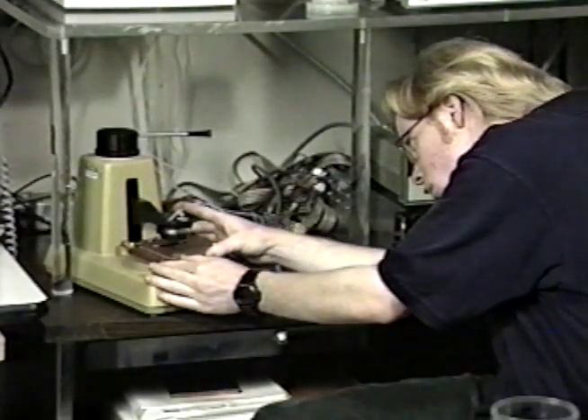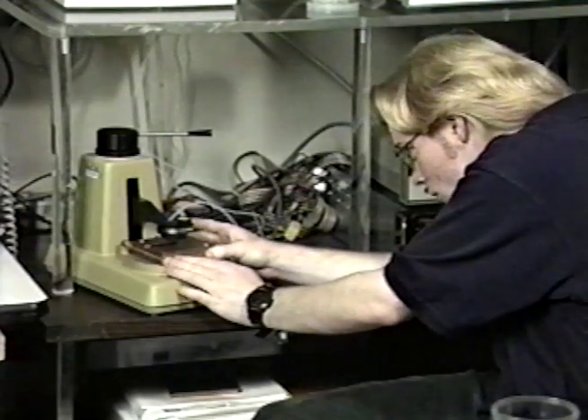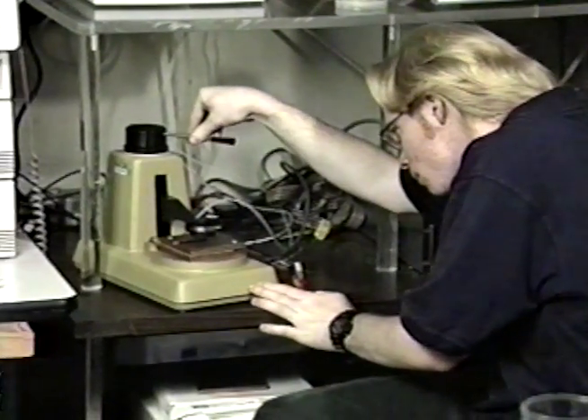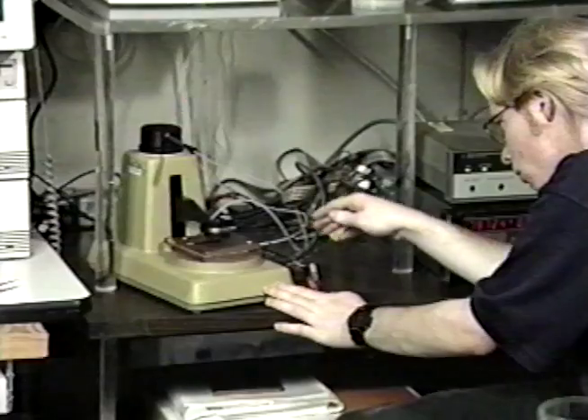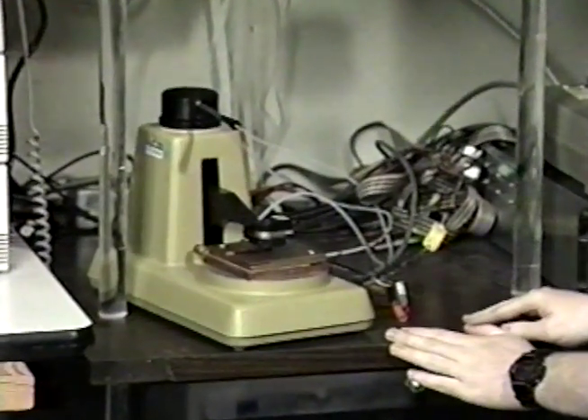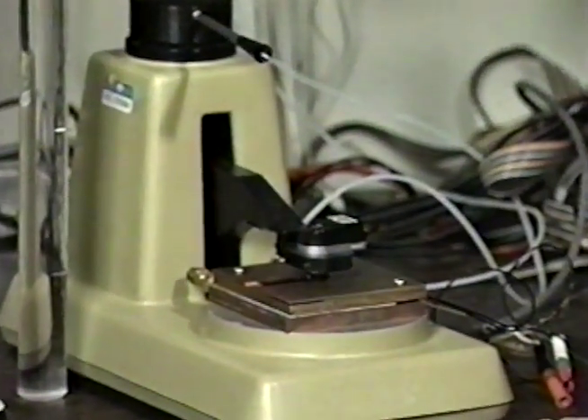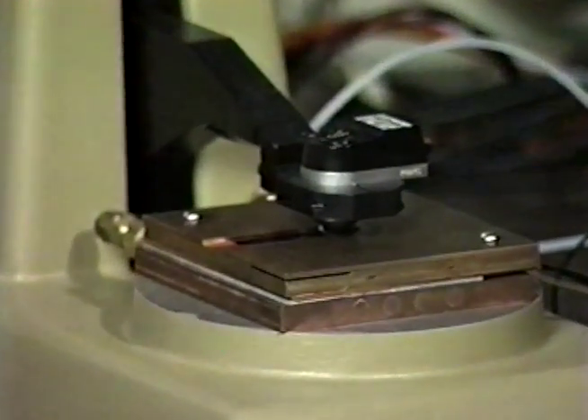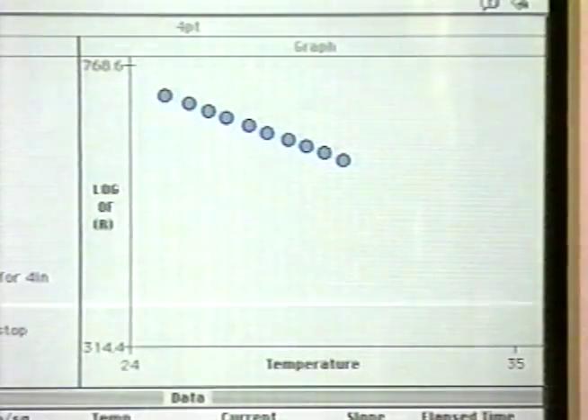This sample is vanadium dioxide film on a silicon substrate, which is being characterized for use in infrared cameras where the temperature dependence of the resistivity is directly related to the sensitivity of the camera. Data is analyzed as it is being accumulated. This data is then stored for later analysis.